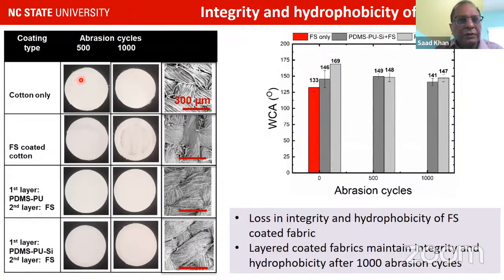If you take cotton only, and we have subjected this to Martindale abrasion, and you do 500, 1000, and we haven't gone to 5000, the cotton would just get destroyed. If you just use fumed silica on the coated cotton, that also gets destroyed. But then if you have these PDMS PU, either with fumed silica or without fumed silica, we see that we do not see loss of integrity. And so here is some quantitative data.